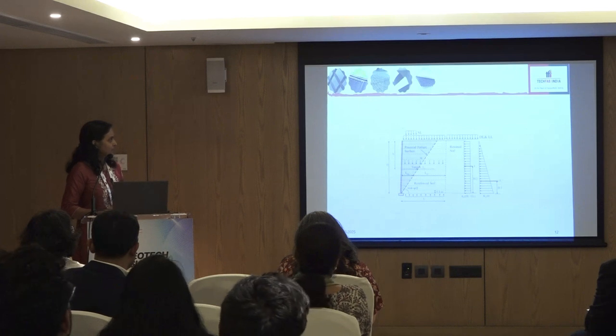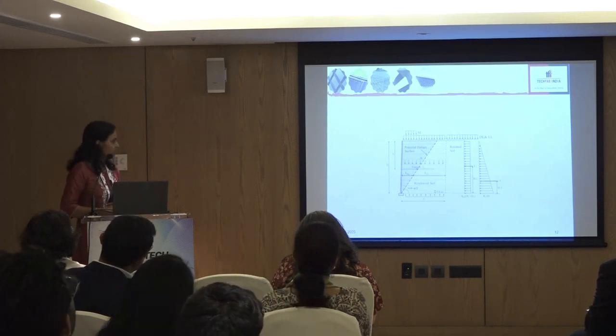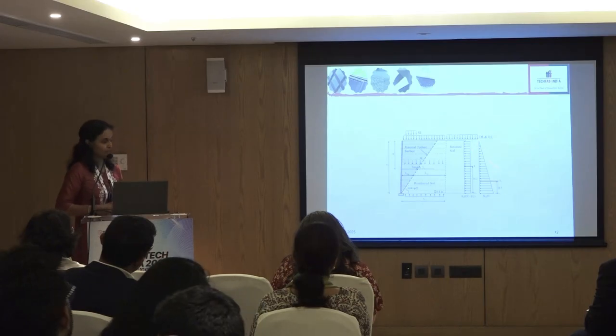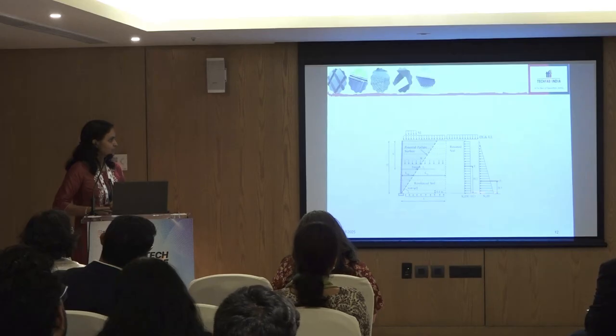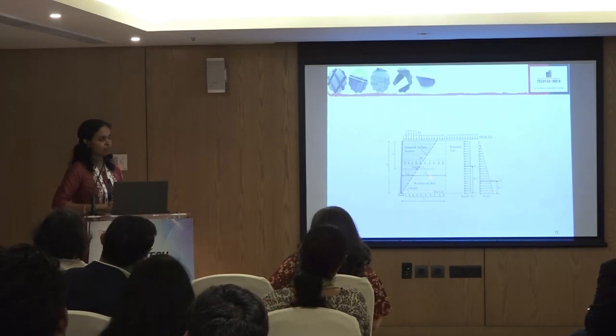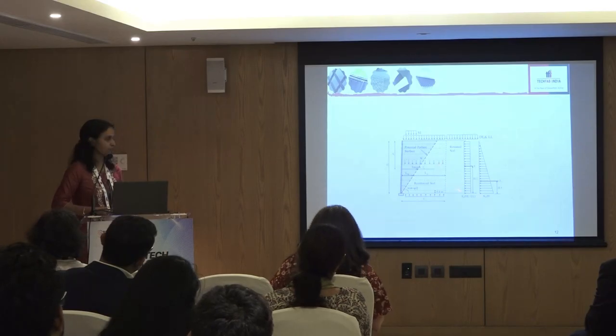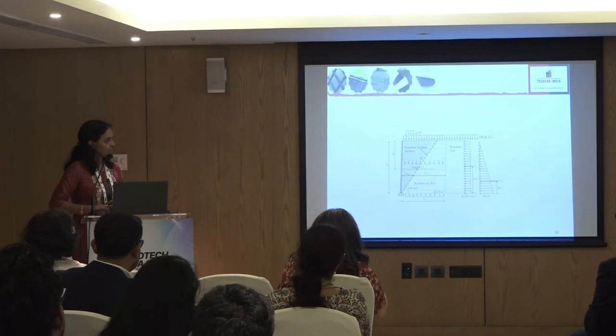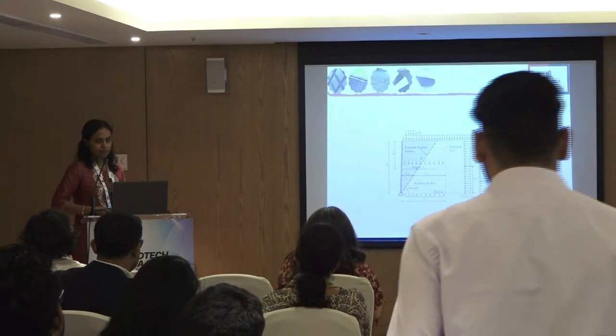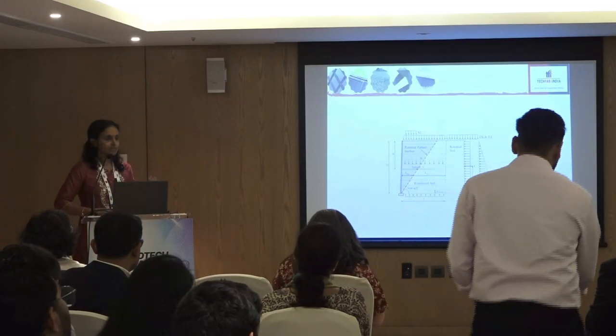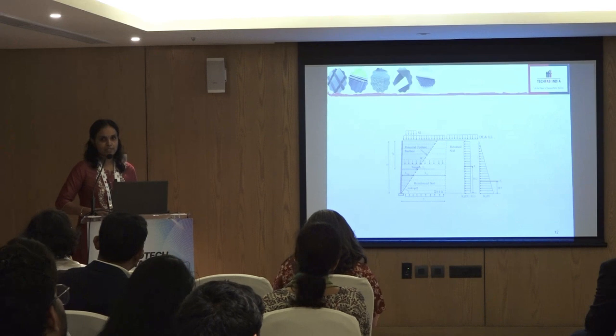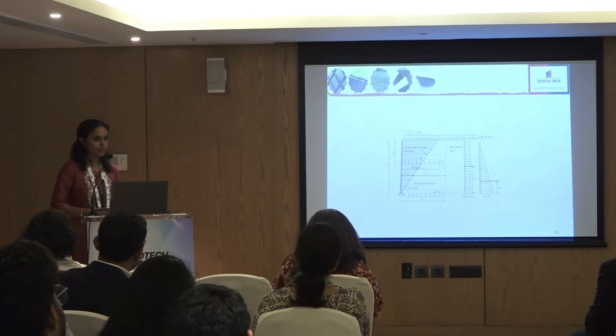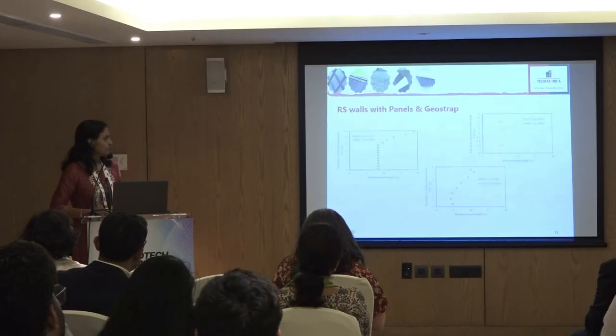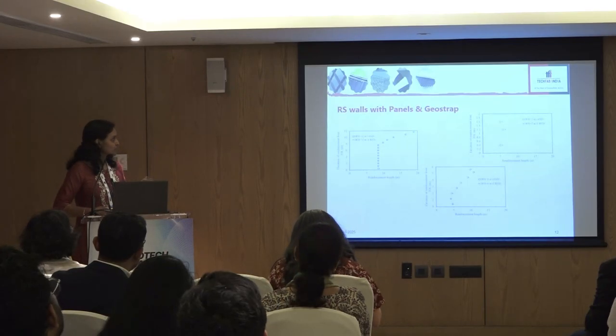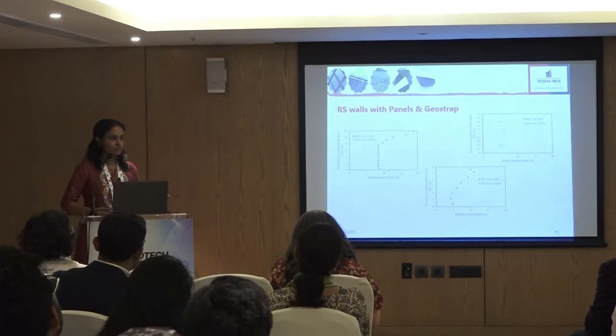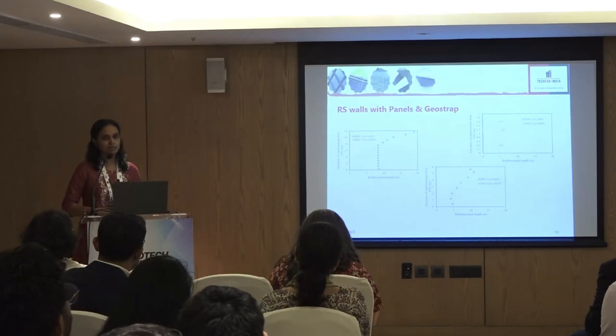Now, we can see that the lateral earth pressure increases with depth of the wall, and so towards here, in direct sliding, the vertical loads have a load factor of only 1, whereas the lateral loads are magnified by 1.5 times. Whereas in ASD method, we are not multiplying by any factors. So LRFD method is demanding more length towards the bottom of the wall. Now in panel and geostrap, we observed that for all the heights, both the methods are demanding almost the same length of the reinforcement.